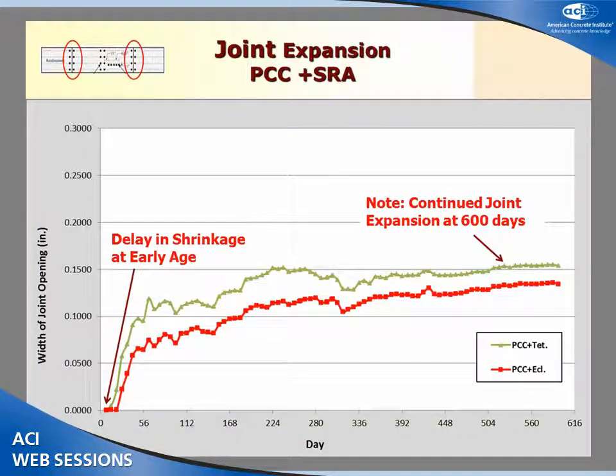Here is the Portland cement concrete with two types of shrinkage reducing admixture joint expansion, and again you see the delays in shrinkage using shrinkage reducing admixture. You can also see the shrinkage in these two types of shrinkage reducing admixture continue for a long time, for about 600 days of our measurement.